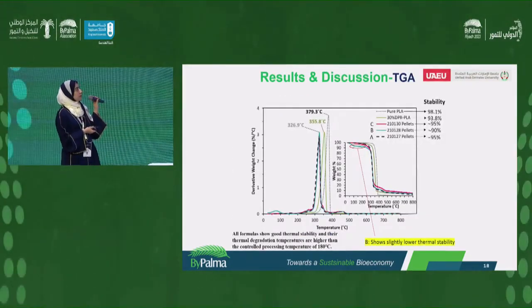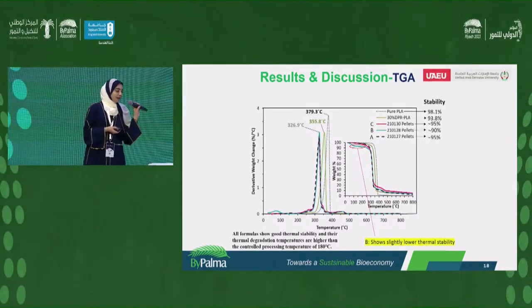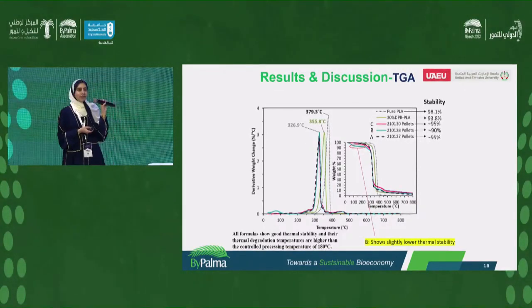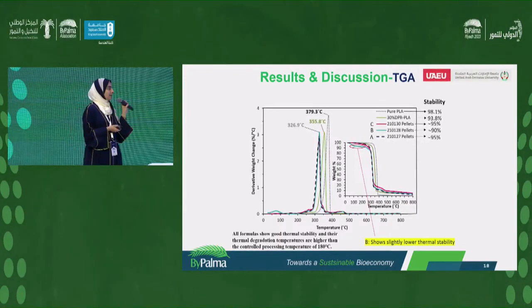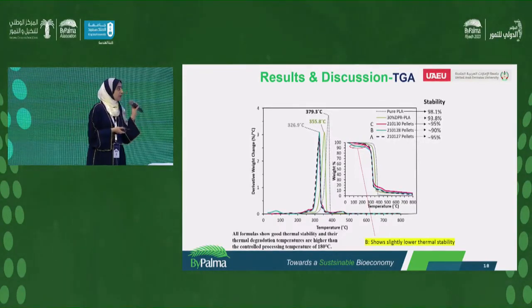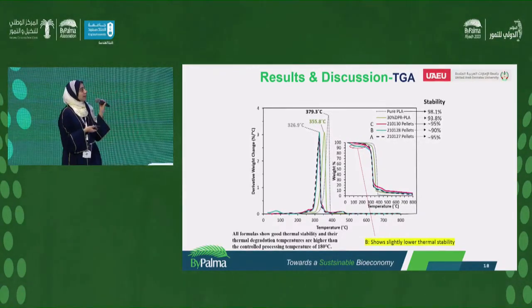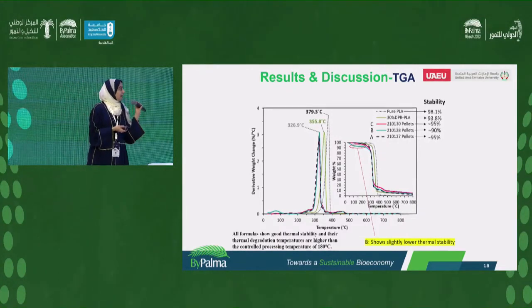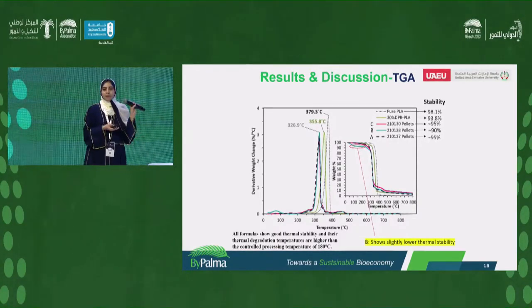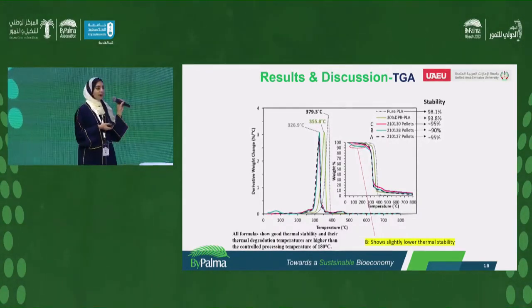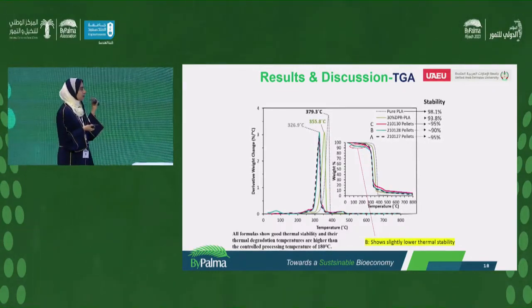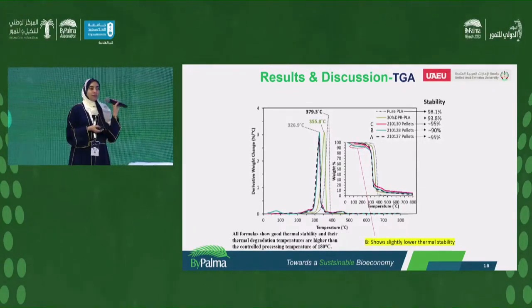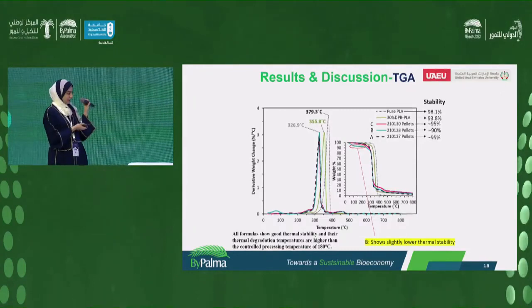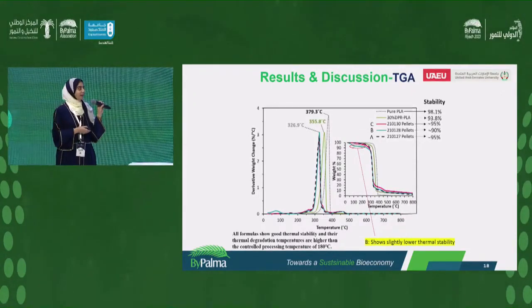We also tested the thermogravimetric analysis for the three optimized samples, and all the formulas showed good thermal stability up to, we can see, up to 95%. And they are all far from the processing temperature of 180, so the degradation temperature is way far from the processing temperature. So the product is safe.